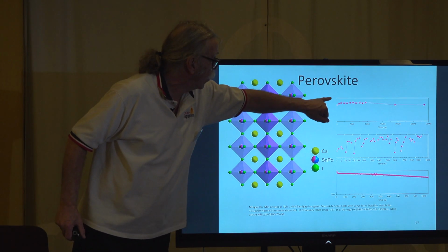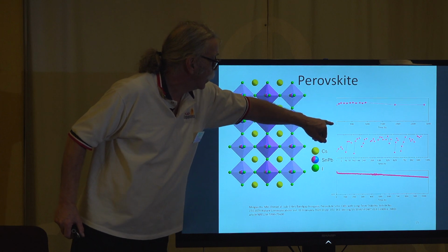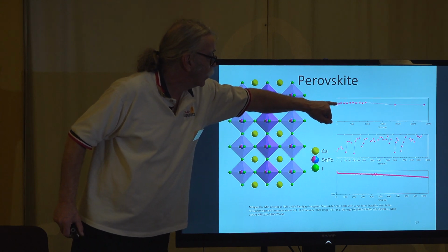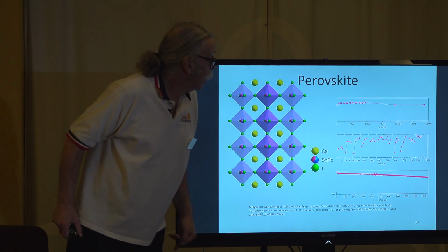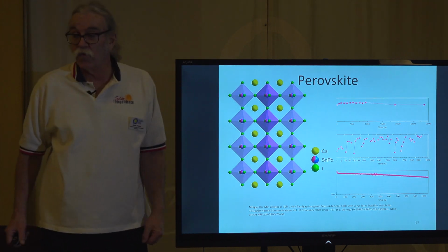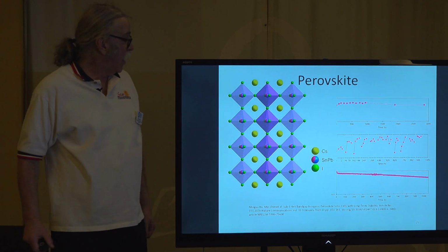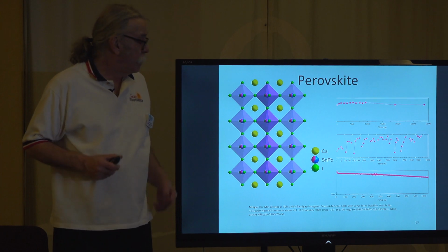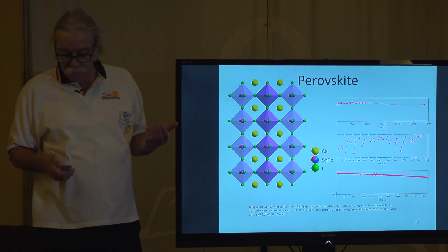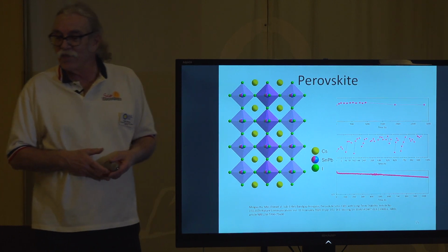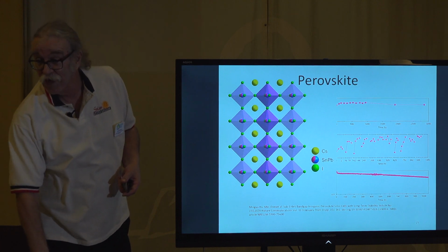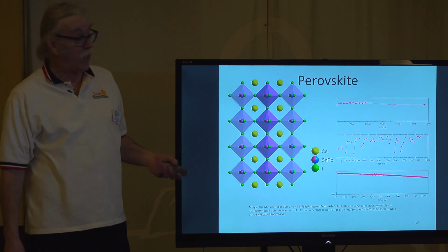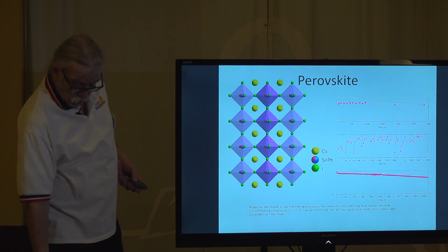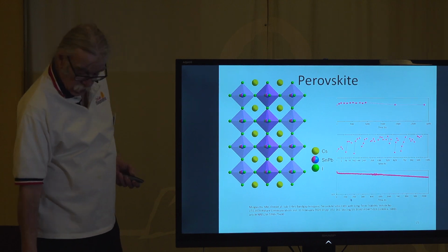This graph is supposed to show efficiency. This is 100%, that's 0, and it's dropping about 20% after about 3,000 hours. Well, that's fine, that's 3,000 hours, but that's not enough for being outside for 25 years, let alone, so that's 3,000 hours on the bench in the lab with their own custom cells that they did at once.